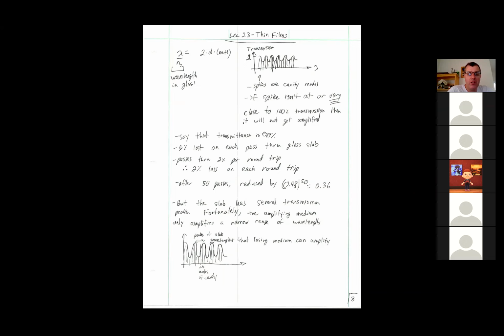Well, 99% transmission still sounds like a lot, except that you've got 1% lost on each pass through the glass slab. And if you go through it twice in a round trip, you get 2% loss per round trip. So if we make 50 passes back and forth, the amount of light that survives is 98% of 98% of 98% and so forth, done 50 times. If I take 0.98 and raise it to the 50th power, I only get 36% of the light saved. I lose 2/3 of the light in 50 passes. And I would get another 36% of 36% if I did 100 passes.